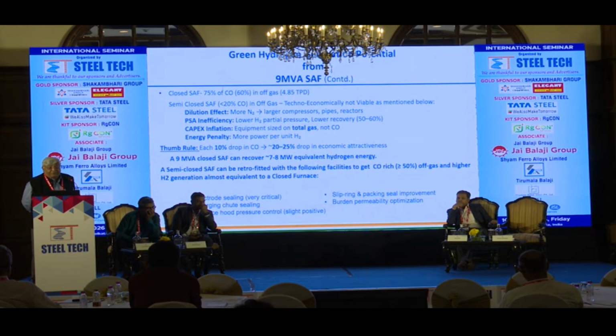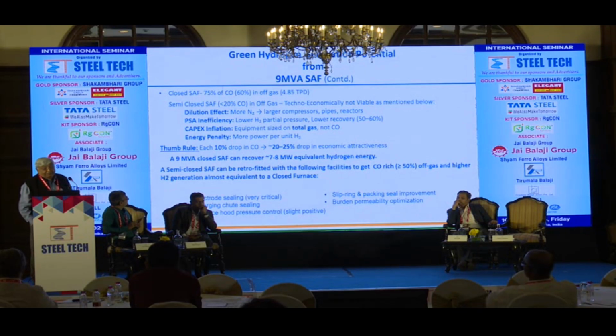In semi-open type furnaces, it is not techno-economically viable because of the dilution effect: more nitrogen, larger compressors and pipe reactors, and then PSA inefficiency, lower hydrogen partial pressure and lower recovery, that is 50 to 60%, and capex inflation, that is, equipment size is based on total gas, not on CO. And energy penalty, more power per unit of hydrogen. As a thumb rule, each 10% drop in carbon reduces the economic attractiveness by 20 to 25%. And a 9 MVA closed SAF can generate around 7 to 8 megawatt equivalent hydrogen energy.